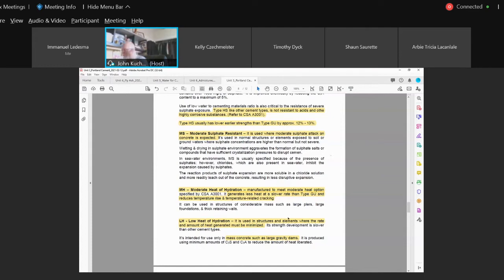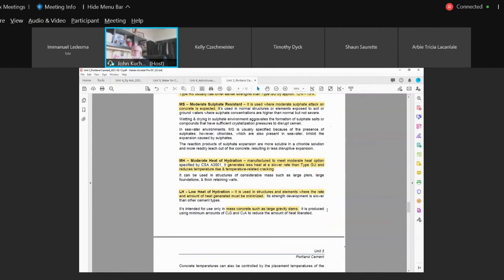So we know that concrete creates heat, we also put heat on it, so we got to be careful. Cold weather concreting is totally different than warm weather or hot weather concrete, and hot weather concreting is different than normal concreting. So we can go on the cold end, we can go on the hot end, and we have to take things into consideration. Are you casting in the Gobi Desert where it's 35 to 40 degrees Celsius, or here in Manitoba? So temperature, ambient temperature, has a big bearing on how a structure and concrete performs. Okay, cements.